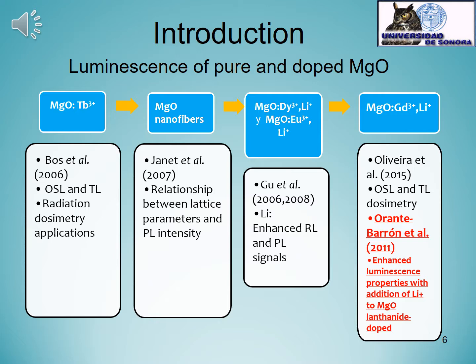And in the case of Gu et al., he previously reported magnesium oxide co-doped with lanthanides and lithium, and they also reported enhanced radioluminescence and photoluminescence signals, but this is not a thermoluminescence study, only for fluorescence.